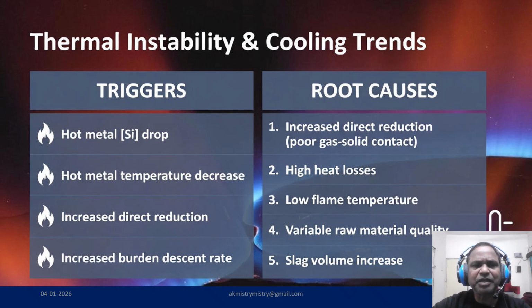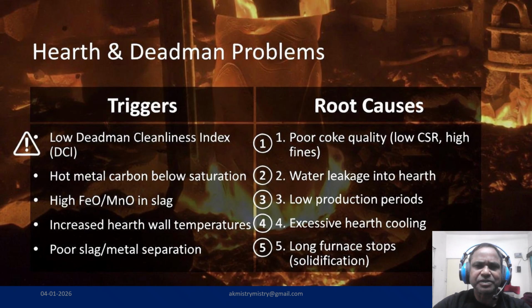Next, let us talk about thermal instability. A primary trigger here is a drop in hot metal silicon or a decrease in hot metal temperature. You might also notice an increased burden descent rate. Why does this happen? Usually it's due to increased direct reduction caused by poor gas-solid contact or high heat losses. We have also come across this in one of my presentations on raceway furnaces. There also it has been well established that variation in the raw material quality and increased slag volume can also drain the furnace thermal reserve, which leads to a cold hearth and nearly chilling conditions.